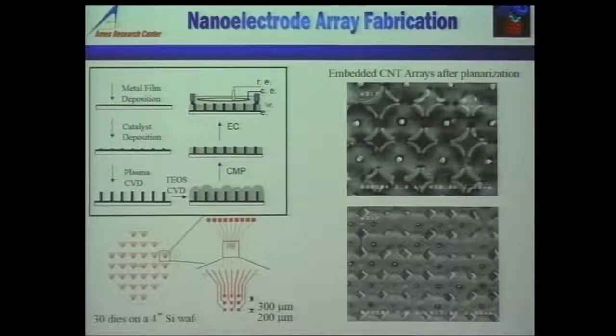So if you take a look at a top view of the SEM image, these white dots that you see are the carbon nanofibers poking out, maybe a couple of nanometers. And then it is actually on a sea of silicon dioxide. So this is the one that we package, and you can bring your probes and attach these probes. The probes could be, depending on the target and what you want to use for a probe, a DNA probe, a protein, an antibody, an aptamer, anything that you want. And this is a carbon chemistry, so you have to have your own protocol to attach the probe. Okay? And then you bring your target. When they hybridize, essentially you can do cyclic voltammetry or electrochemical impedance spectroscopy. Okay, so this is a nanoelectrode.